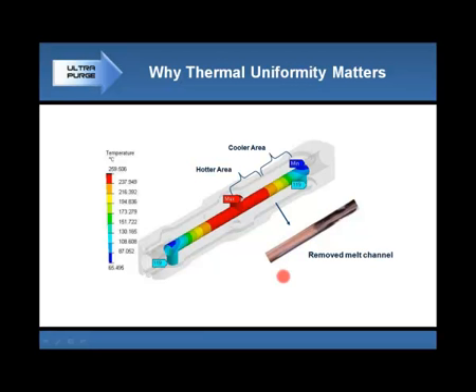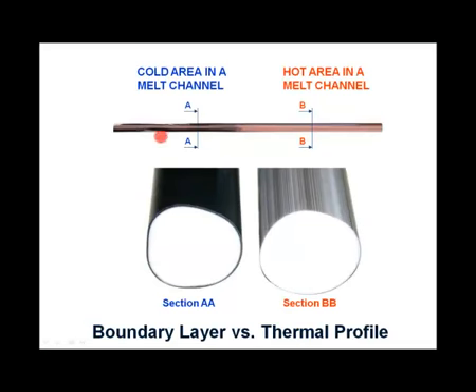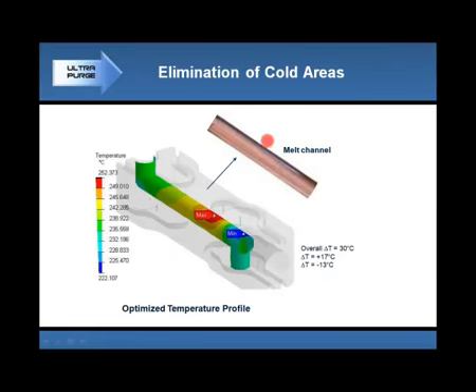Again, as you can see from this little picture, if the temperature of the melt channel is not uniform, we're going to have areas that are very hot and areas that are very cold. You can see that where the cold area is, more color tends to stick on the wall of the melt channel. This is the same melt channel with different sections, and you can see that the cold area is covered by a black layer of color, while the hot area has a lot less black color. The reason is that the more we increase the temperature, the better the plastic will flow, so the easier it will be to remove the previous color. The same analysis can be done in this particular melt channel, where, if we don't have a uniform temperature, we will again have problems with color hanging in the melt channel.